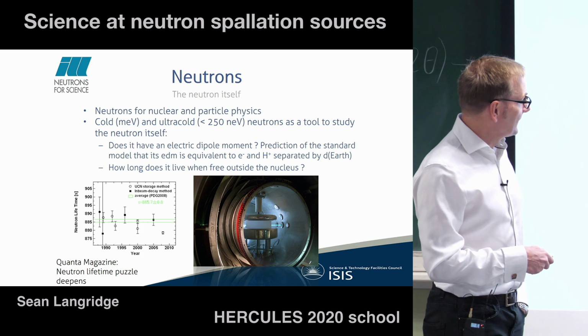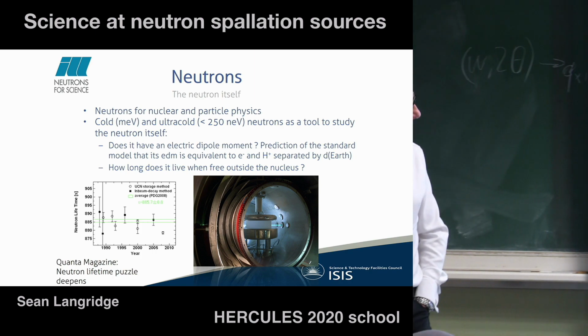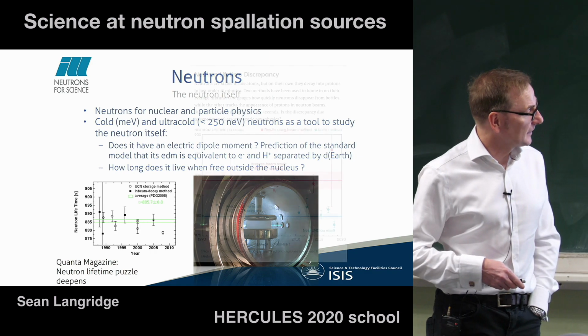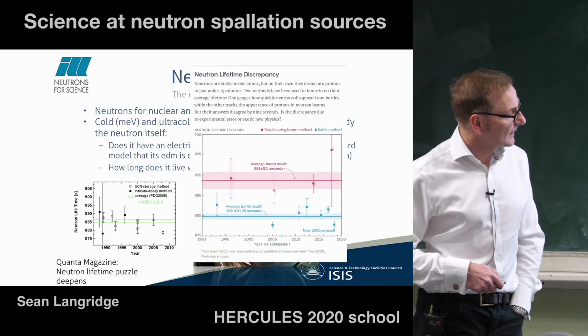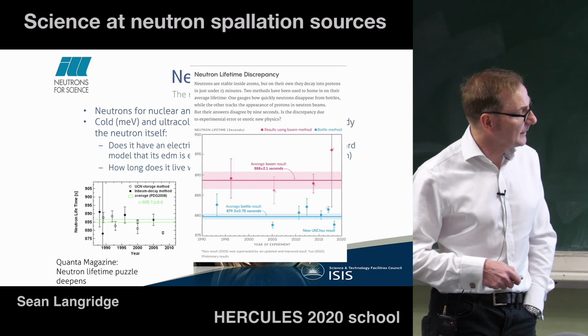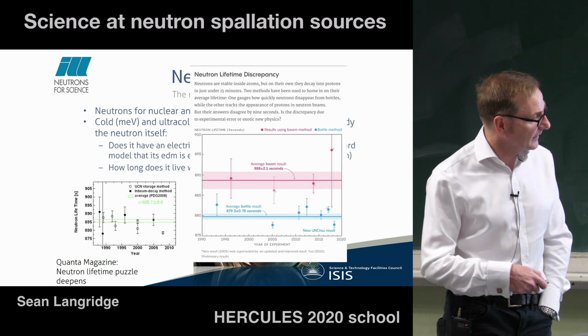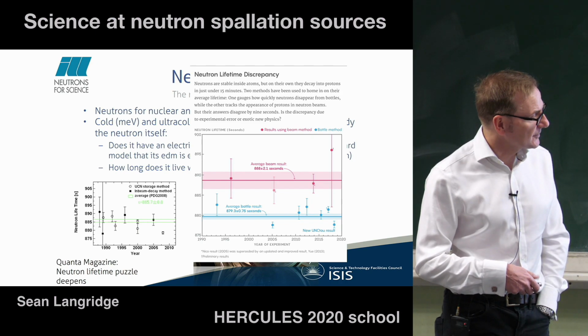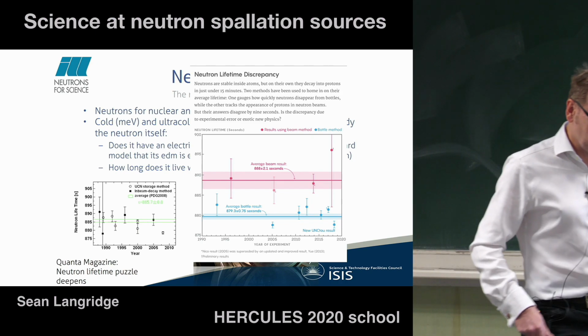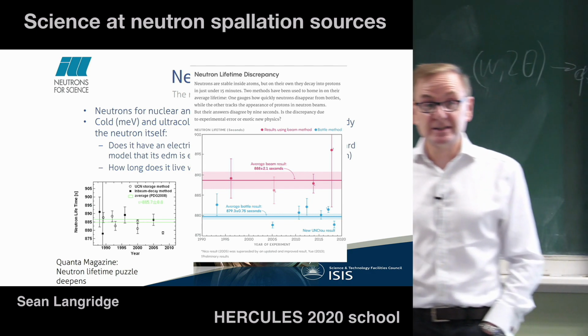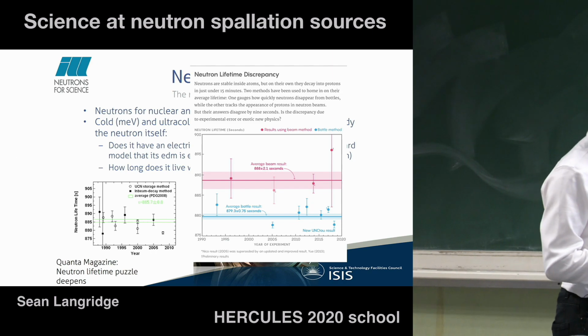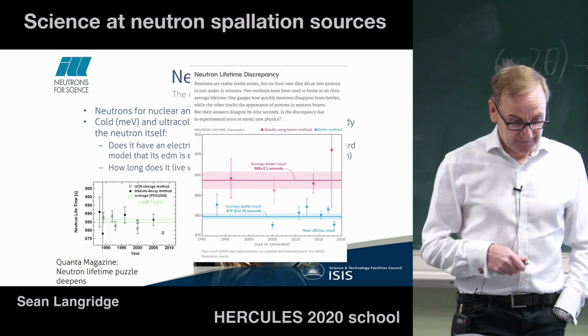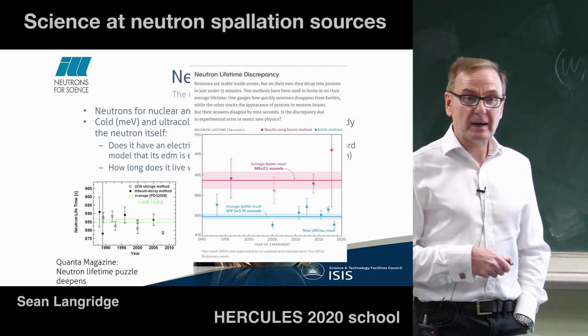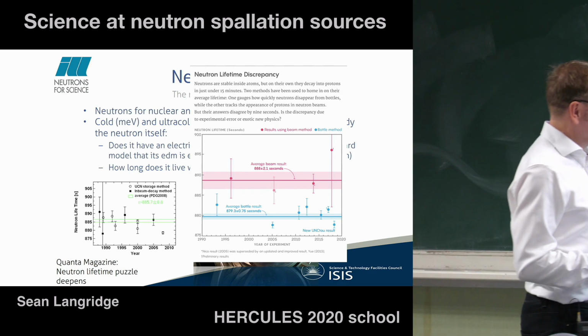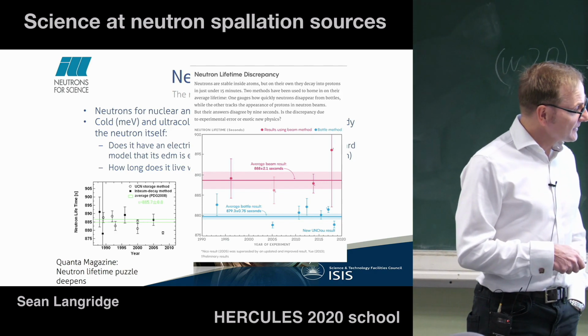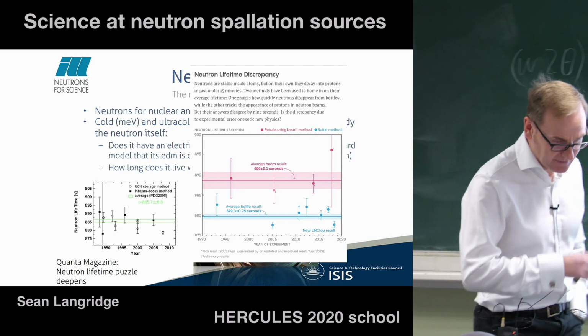And more interestingly, in my view, how long does it live outside the nucleus? There's an interesting anomaly, because if you measure it in two different ways, if you measure it through looking at decay from a beam of neutrons, or you put ultra-cold neutrons in a bottle where you store them, you get different lifetimes. So it's about 15 minutes, but you find the two techniques give you a 9-second difference between the two probes. And so there are lots of ideas as to why this is happening. Some include dark matter, that you're losing neutrons that go into dark matter. But it's still not resolved, but clearly hugely interesting. But let's get back on track.